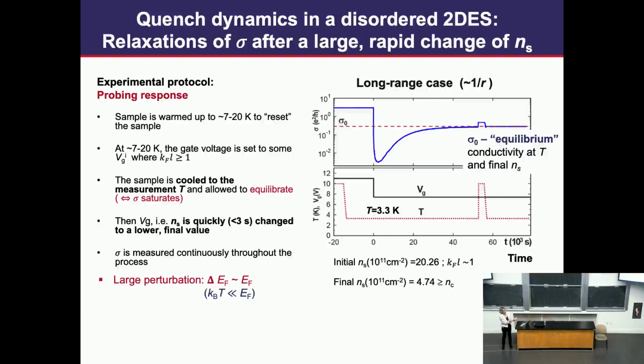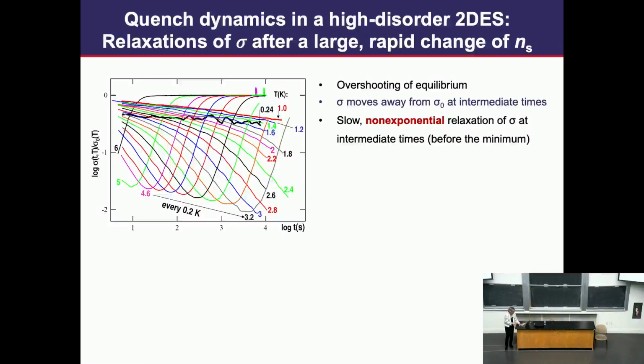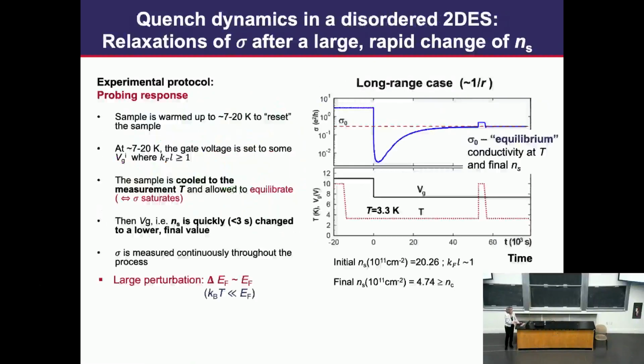Then at much later time, several hours on these time scales, it approaches this dashed line. We check that when we warm the system up and cool it back down again, we get the same value, so we know we waited long enough. So we're calling this the equilibrium conductivity.